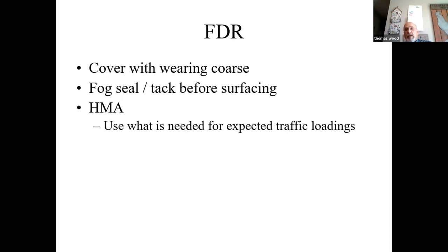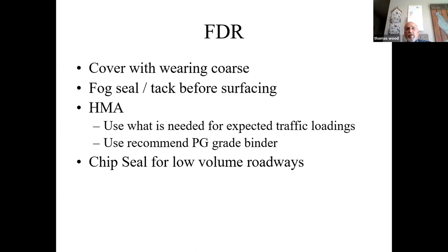Use what is needed for the expected traffic loadings, and use the recommended PG grade binder. So here in Minnesota, MnDOT's position on new construction is a minus 34 for the low temperature oil or binder.